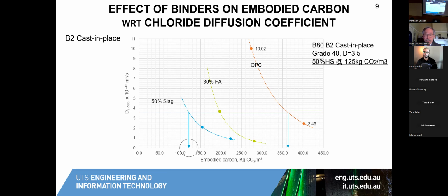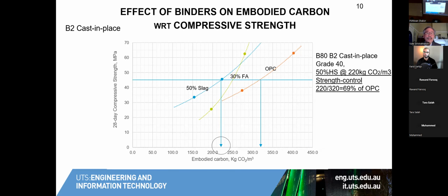What about the strength requirement? With a grade 40 requirement, we are looking for a mean strength of around 45 megapascal. So in this case, slag also is the mix that will give the lowest embodied carbon compared to the 30% fly ash mix or the OPC concrete mix.